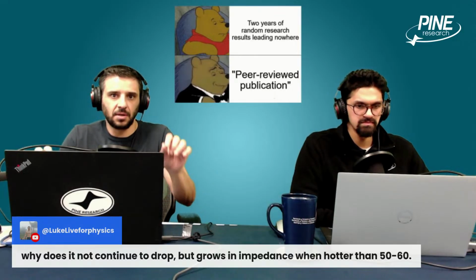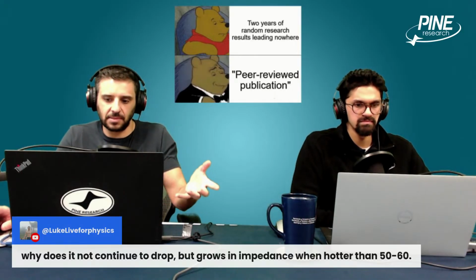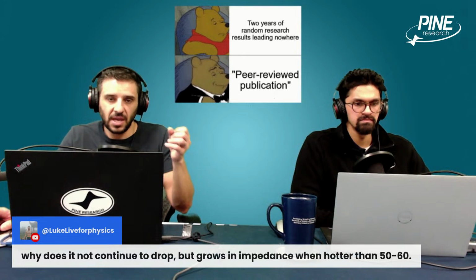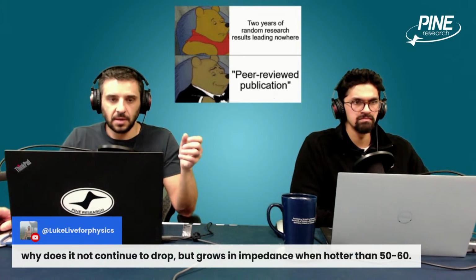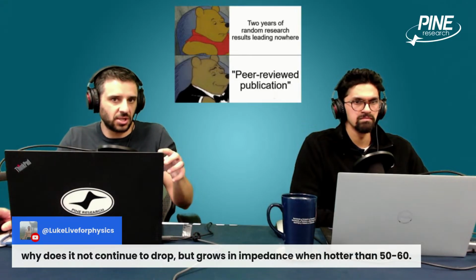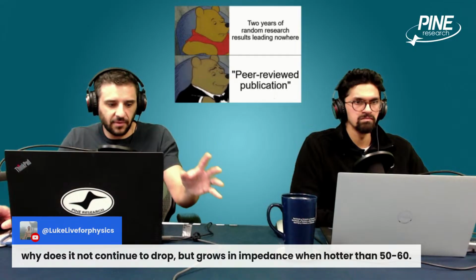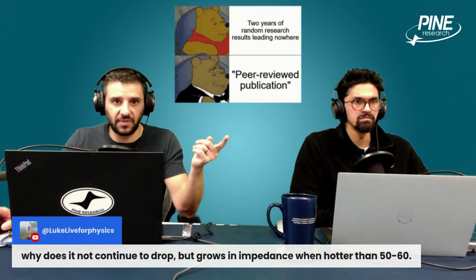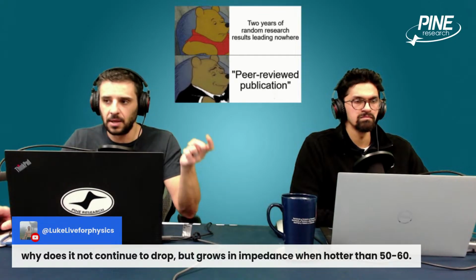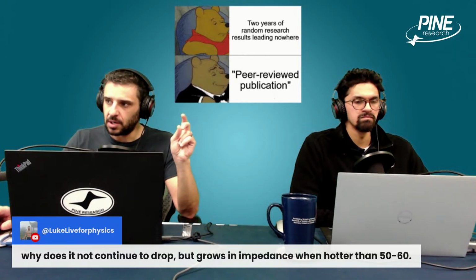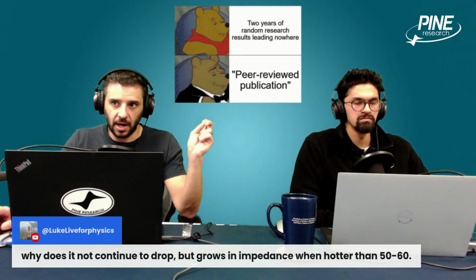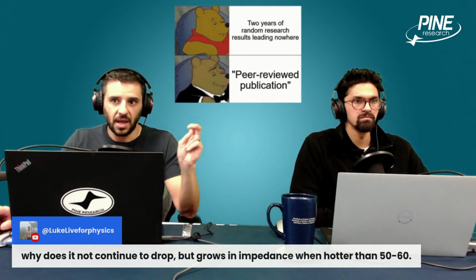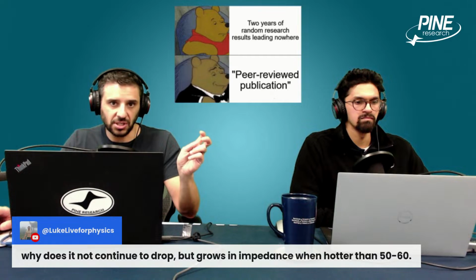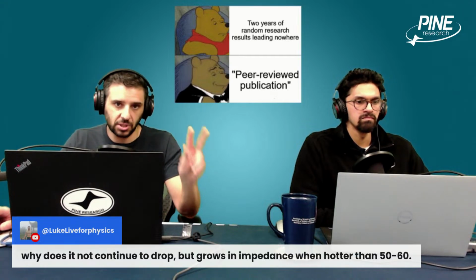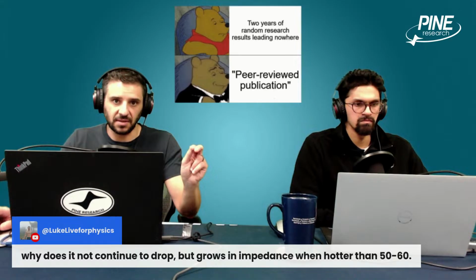Again, don't take this as specific. I'm just providing a possible answer, because these are things that we know do happen as you heat up a composite material. Some of the elements might have a tendency to change crystal structure or phase, or they leave. As one specific example, with lithium cobalt oxide, when you over discharge it, you're putting lithium into it. As you continue to put lithium into it, the oxidation state of the cobalt changes. If it changes too much, it becomes cobalt +2, which is not conductive, and you lose activity.